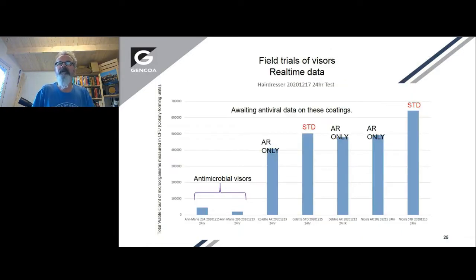So essentially, if you look at visors which are just standard or had an anti-reflection coating, there's a significant microbial loading on these surfaces after we studied them. But the visors we had coated with our antimicrobial coating had a much lower count of bugs on them. So that's really amazing. We have a transparent coating for plastic that actively kills bugs on the surface.